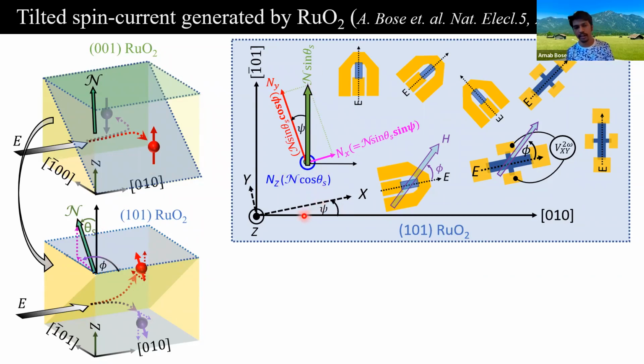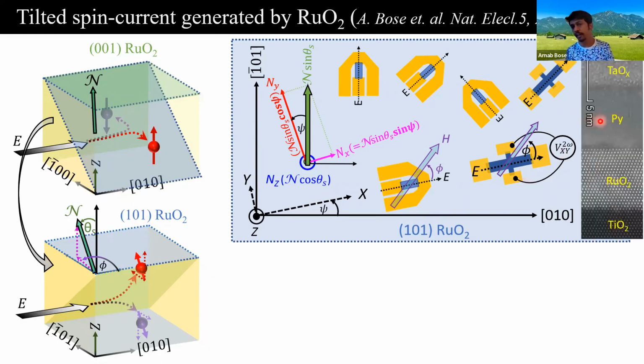And now if we run current along a certain crystal axis, for example, at an angle psi, then we'll have further projections of the Néel's vector perpendicular to the direction of current and along the direction of current. Meaning in this plane, the 101 plane, we will have all x, y, and z components of spins. And this is what we want to experimentally measure. For that, we need to have a probe to detect the spin currents. We have permalloy on 101 oriented ruthenium dioxide.